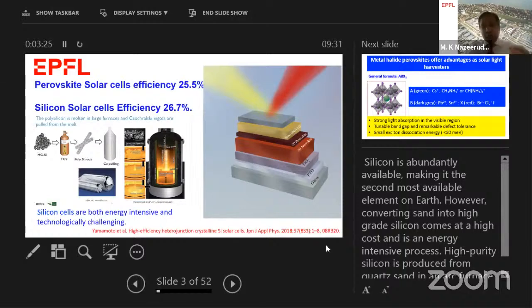Now we deposit perovskite material on top of it, and then I have a very thin layer of 2-dimensional perovskite. The students who want to know more about this will see it 15 slides later, what a 2-dimensional perovskite is. This is quite interesting material. You will learn a lot about these 2-dimensional perovskites. Then we have a hole transporting material. Basically, the perovskite solar cell has 3 main layers: one, electron transport layer; perovskite as absorber layer; and hole transporting material, spiro-OMeTAD.